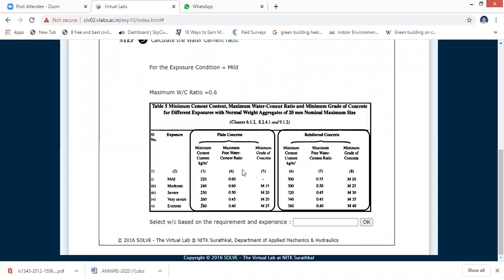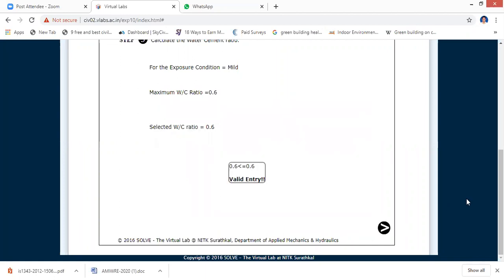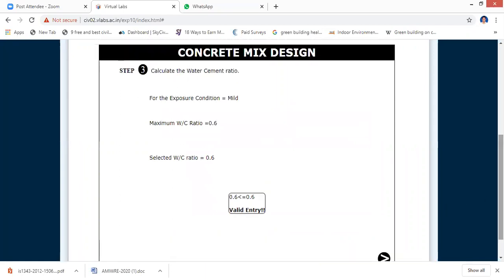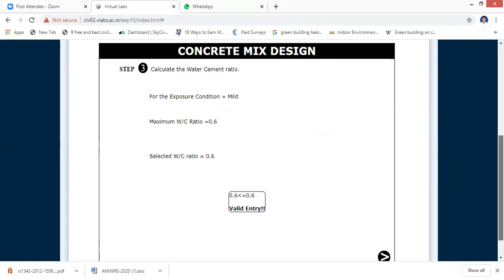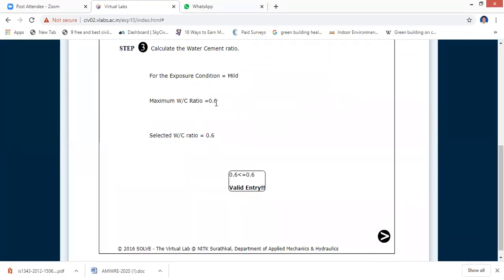So when we choose plain concrete, what is the exposure? Let us consider mild, and minimum grade is not given. If it is moderate for M15 grade, it is 0.6. Okay, let me take 0.6 as per the code. Then okay. See, this is the procedure. If you know how to start mix design step by step, you can teach anyone. So for the mild exposure, the maximum water cement ratio is 0.6, and I have selected 0.6. So valid entry, 0.6 is equal to 0.6.